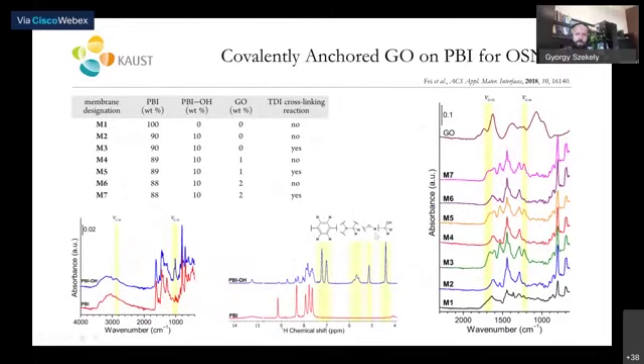So again, we looked at the characterization of the membrane after this covalent anchoring. So why is it important that we use covalent linkage? The literature before basically blended GO into the polymer matrix, prepared the membrane and used it. But in the long term, the GO can leach out. The polymer chains usually rearrange, and it gives way to the GO to escape from the membrane, contaminating your product and also decreasing the membrane performance. So to avoid this deterioration of the membrane, we hypothesized that covalent anchoring would be the solution.